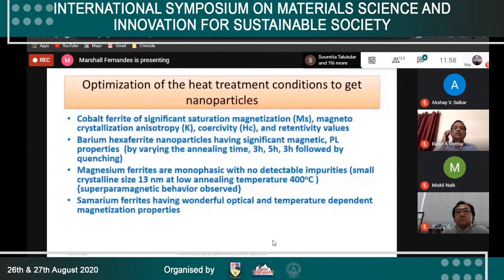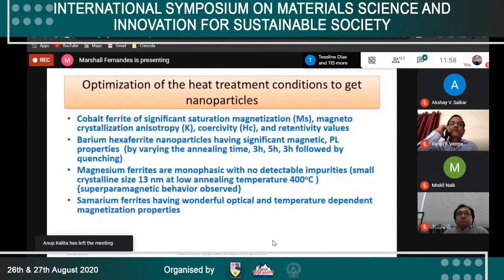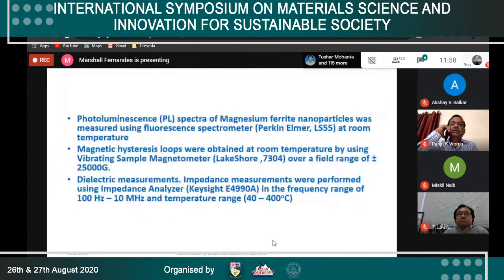Samarium ferrites, as I was telling just now, have wonderful optical and temperature dependent magnetization properties. This could be prepared by the citrate precursor method by heating the citrate precursor up to a particular temperature for a certain time, which was standardized, and the temperature was chosen on the basis of the peaks in the differential scanning calorimetry analysis, understanding the thermal data.